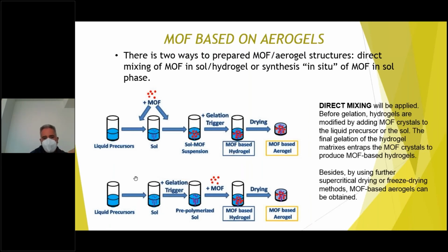Basically, the fabrication of aerogel passes through a first step, that is to have a liquid precursor where we mix and disperse the MOF material. We have a sol-MOF suspension, and then an important process happens, that is the gelation trigger. In this solution with the MOF dispersed inside, we make a polymerization process. We make a sol polymer, and this salt polymer is what we name a hydrogel. The hydrogel has basically three components: the MOF very well dispersed, the polymer, and the solvent. If we are talking about a hydrogel, the solvent is water, of course.